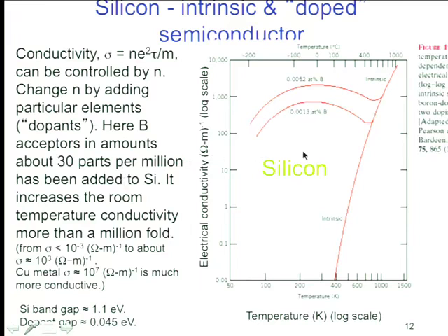This particular graph is a very early one. It was actually a paper in which the name here, I don't know if you can read it, is Bardeen. He won the Nobel Prize for this work, inventing the transistor, which is, of course, the basis of all our electronics these days. And what they noticed was that you could get, by adding, let's see if I can read that, 0.0013 atomic percent. That means it's really 0.000013 atoms per silicon atom, sort of like 1 in 100,000.